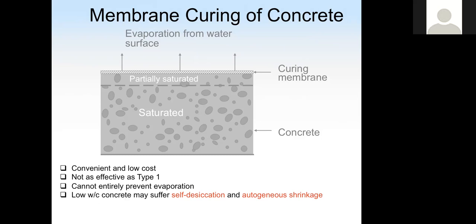For this type of curing, if the concrete has lower water cement ratio, the concrete may suffer so-called self-desiccation. Okay, so self-desiccation is drying off the concrete because the water cement ratio is so low. So hydration will consume a lot of water. If the water to cement ratio is very low, I will say less than 0.4, then the pores inside the concrete may be dry due to hydration. Okay, so that may cause the concrete to shrink, and that type of shrinkage is called autogenous shrinkage. We'll talk about this more when we talk about shrinkage of concrete.